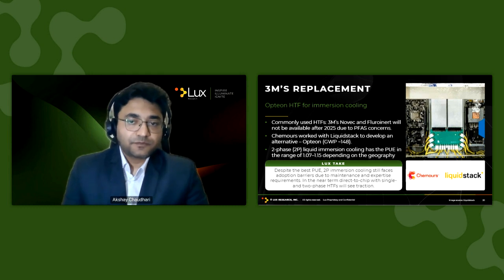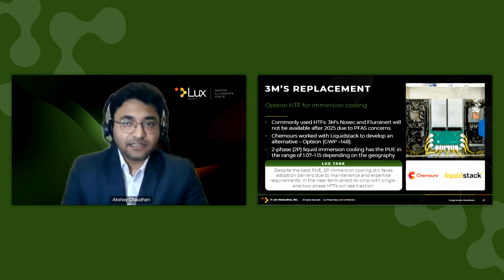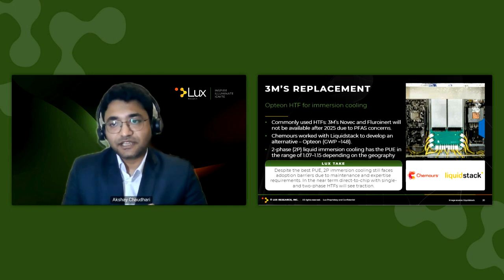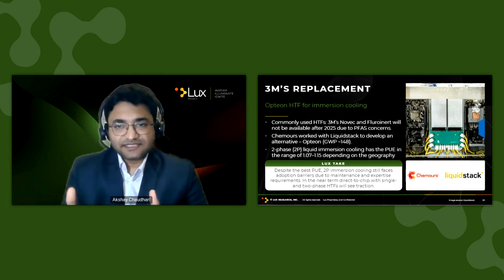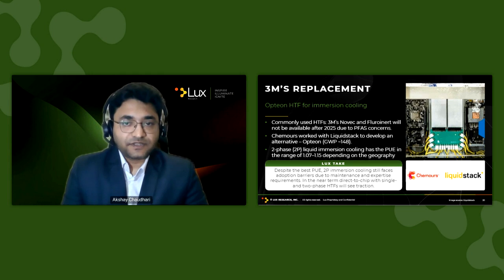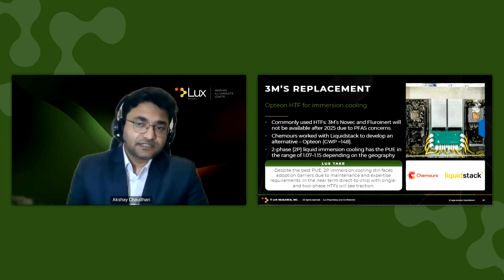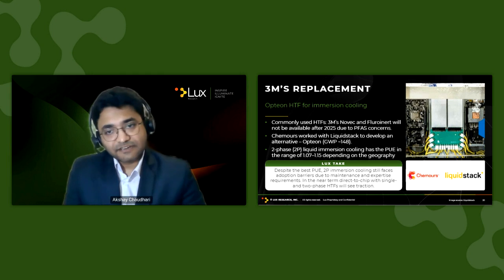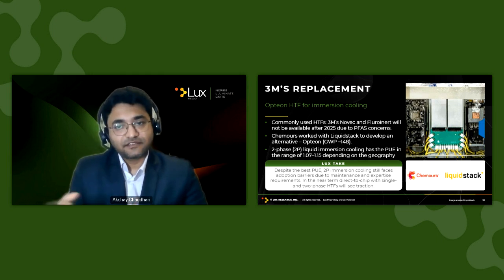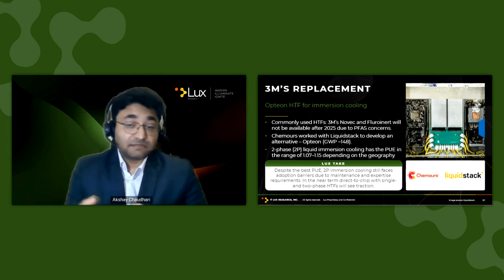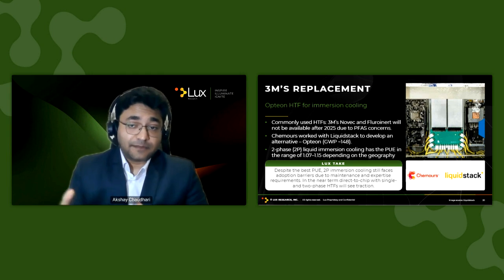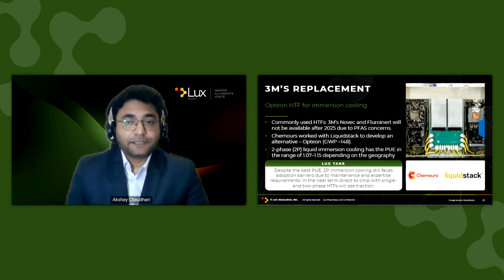The GWP and the handling requirements in large-scale data centers have basically slowed the adoption of these two-phase liquids. And as a result, in the near term, two-phase liquids are more likely to gain traction in closed-loop systems like direct-to-chip cooling, rather than applications in two-phase immersion cooling.